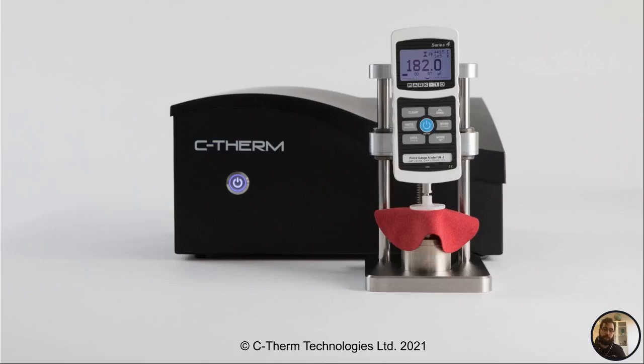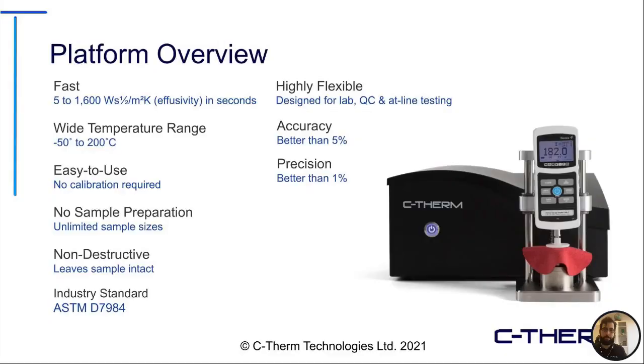But today's focus will be around the TX Touch Experience platform in measuring warm feel and cool touch. This includes the controller to drive the sensor, the MTPS sensor, which is underneath this neat punch out of the red textile here, and control of the compression over top of the device. In terms of effusivity range, you have from the effusivity of air, around 5 watt-second-half over meter squared Kelvin, up to the effusivity of water, so a fully saturated textile, at 1600. This can be introduced into a temperature range from -50 to 200 degrees C.